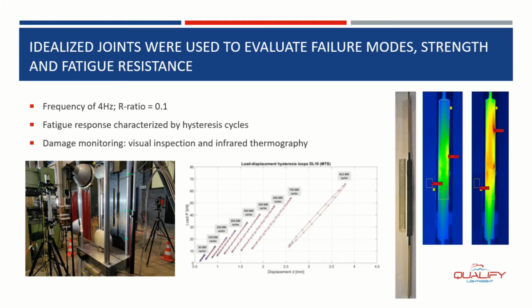If we go a level higher, we are looking at the structural joints themselves. We are looking here at an idealized joint. It's a double lap shear specimen with an overlap length of 2 × 150 millimeters. It's the black part in the image at the right, painted in black to be able to follow temperature evolution